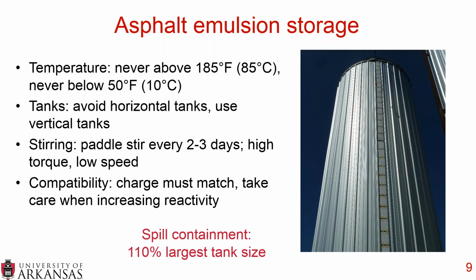Another very important part of all types of storage is spill containment. You want to make sure that your entire manufacturing facility is surrounded by a spill containment, and that containment needs to hold the volume of 110% of your largest tank size. And that's so if your largest tank gets a hole in the bottom of it and completely drains, it can fit within your spill containment. And this can be anything from an earth berm to a concrete wall. Again, if you go to a different emulsion facility, they all are slightly different, but you want to make sure you're able to contain any sort of spill if a tank does happen to get a hole in it.